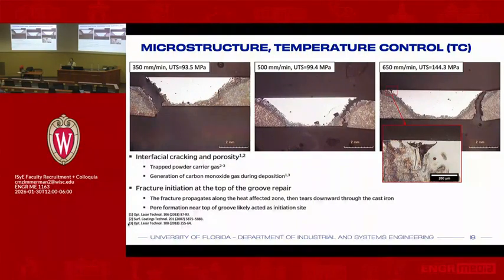And I mentioned that heat affected zone because that's what we're going to be focusing primarily on, how much you can actually control that. And you can see that in this particular graph, when you have different speeds, you can see that heat affected zone again, and you can see how it actually has a big impact, one, in the amount of porosity that you have in that interface, and the second one is going to be on how controlled that band of heat affected zone is in comparison to the lower speeds. You can see that the lower speeds are just an opportunity to be able to trap air, and then you get porosity in it.